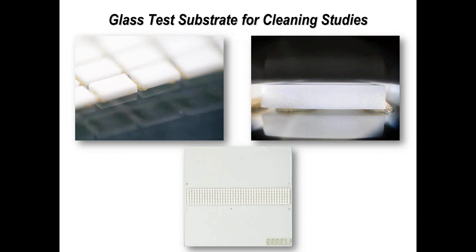This slide shows a close-up of the glass test vehicle and the ceramic parts mounted to the glass. Typically, when doing cleaning studies I mount four of these in the bottom basket of a dishwasher-style cleaning process and four in the top, to see the performance difference between front, back, top, and middle of the cleaning process. You could also position them in a batch process basket or use them for an in-line process. It tells you the performance of your process before you go into expensive laboratory studies — no point doing laboratory studies until you have confidence your process is right.